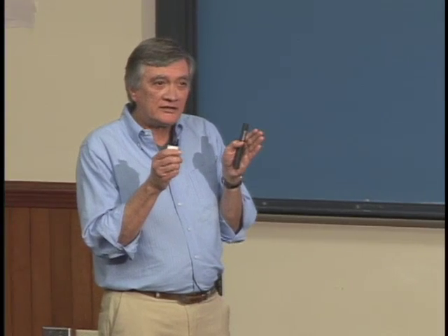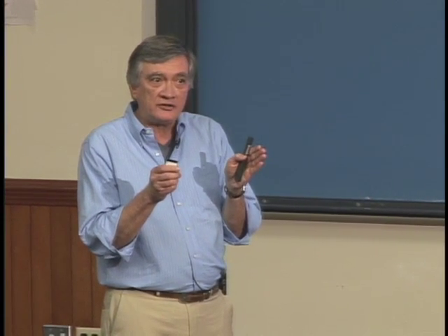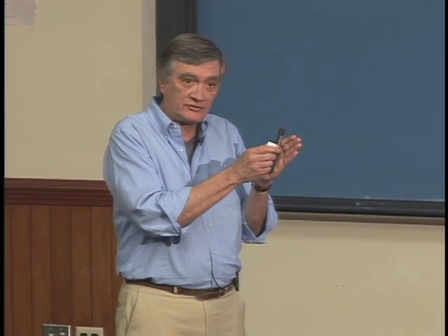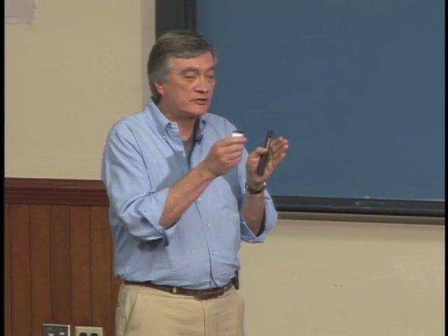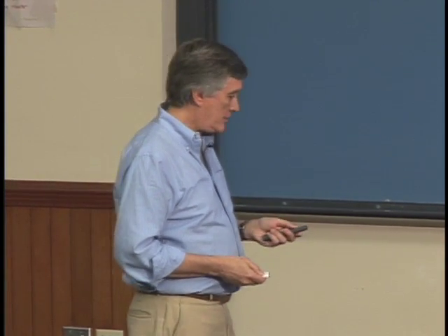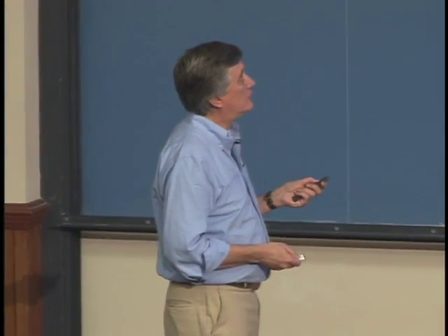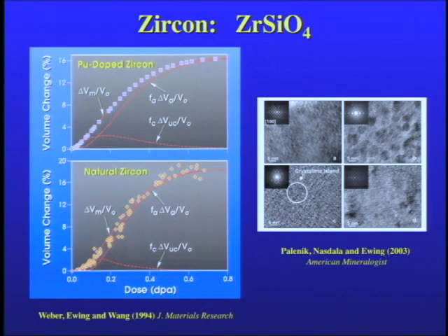So this was a way to examine how materials changed as we followed the progress from crystalline to metamict state. The other very interesting experiment was to dope zircon with plutonium, about 10% plutonium, and see the accelerated damage process, because the plutonium, in this case 238, has a short half-life, and so the damage would accumulate quickly. And the surprise was the damage accumulation curves and the models for the damage accumulation were very similar for both.